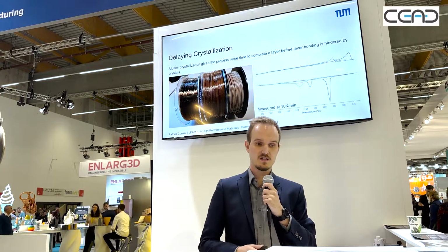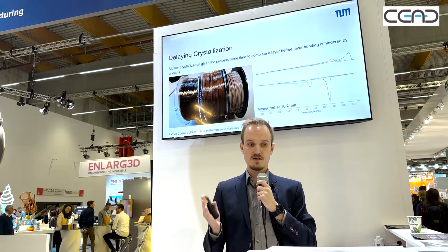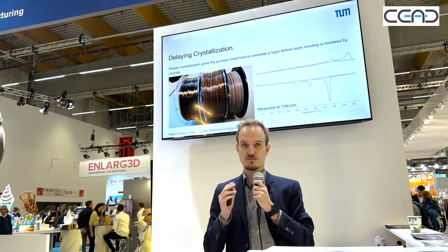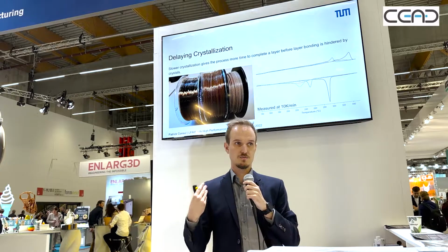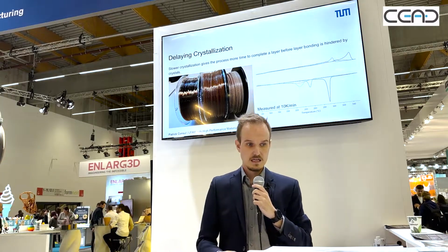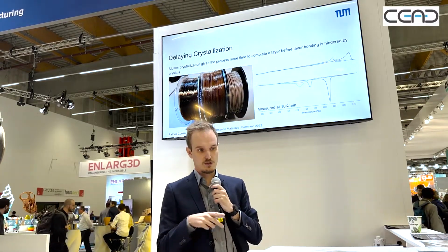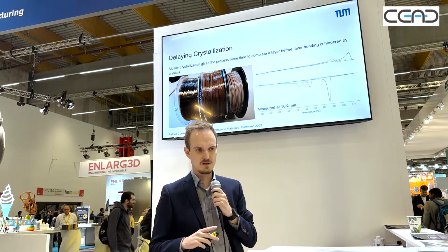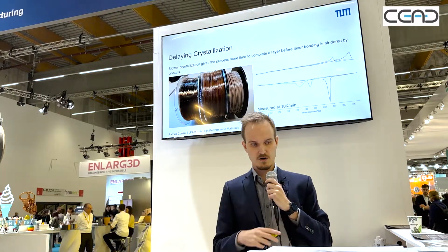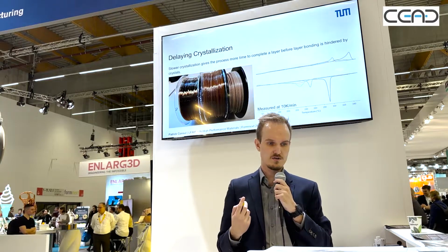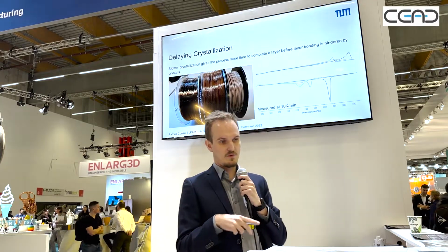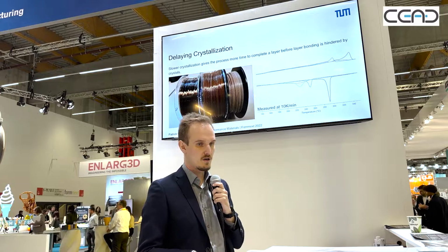And you can also see it in the DSC diagrams, that the peak not only moves to lower temperatures, but it also becomes wider, which means the crystallization happens slower. And we ended up going for the slowest crystallizing one. I don't think that one's been commercialized yet. The middle one is now known as AM200, if I'm right. We opted for the even slower crystallizing one because